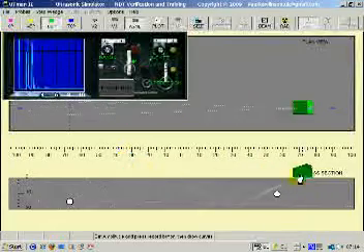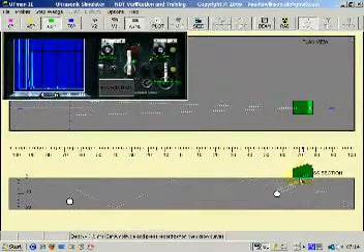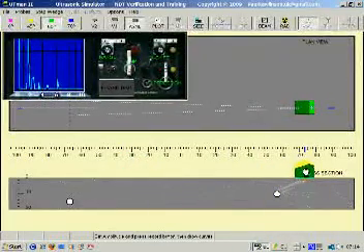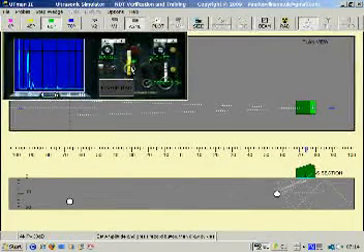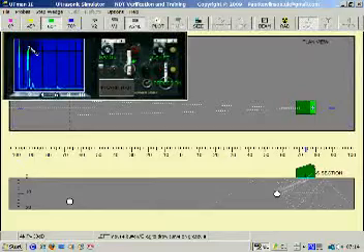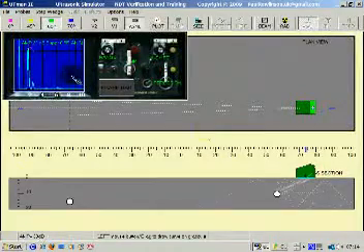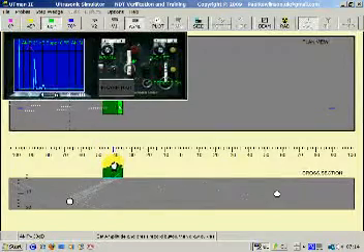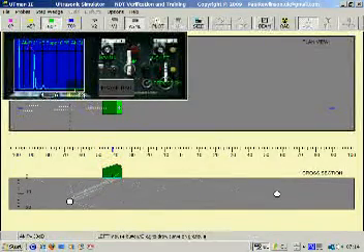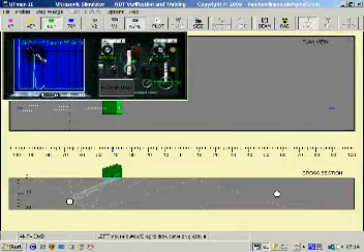So as you get close to a defect, like this hole here, this flat bottom, this through drilled hole, you reduce the amplitude to about 80% and then mark the top of it with an X. Move to the other hole, which is the same diameter, but because it's further away, it gives a smaller response.